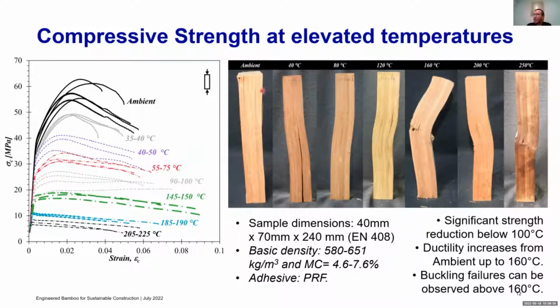But what we saw is that as we start increasing the temperature, you will have a decrease in the compressive strength of bamboo, but we also observe changes in the failure modes. And we move from having pure crushing failures into having larger deformations, and then bamboo starts pretty much buckling when the temperatures were above 160 degrees.